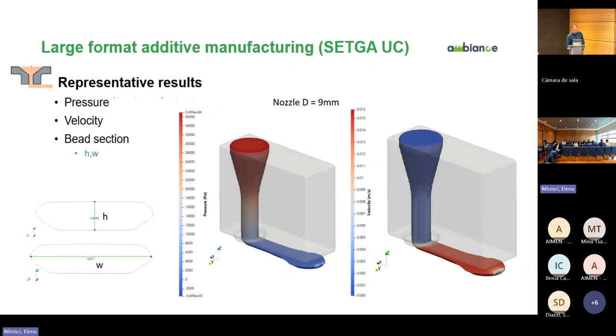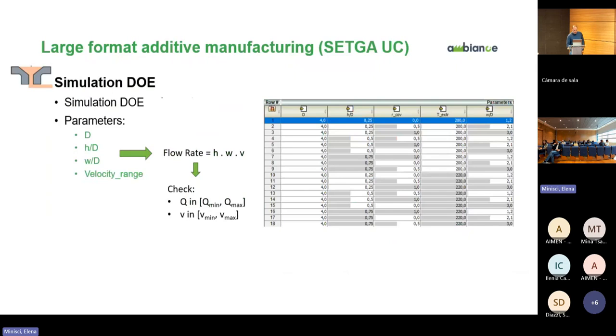We can access, as before, the full distributions of pressure or velocities. But in this case, we are quite interested in the resulting section of the filament that we can parameterize in a simple way by the height and width. These parameters are extracted from every combination we make in the simulation. So as before, we define a DOE. In this case, we cover the different diameters that have been used in the real fabrications, and we parameterize as a function of this diameter, because in additive manufacturing, there are several ranges recommended for the height and the width of the filament as a function of this diameter.